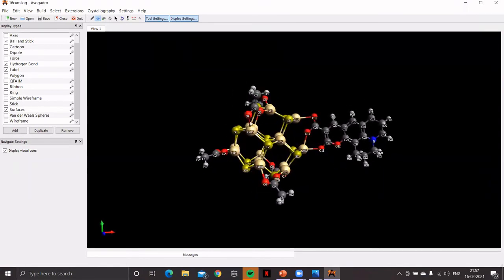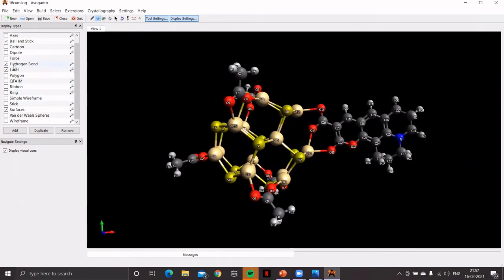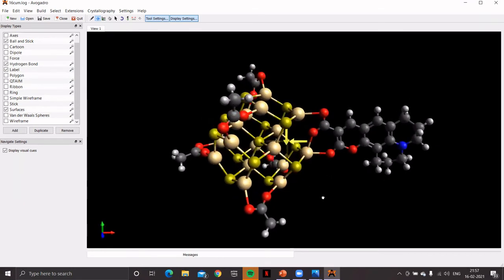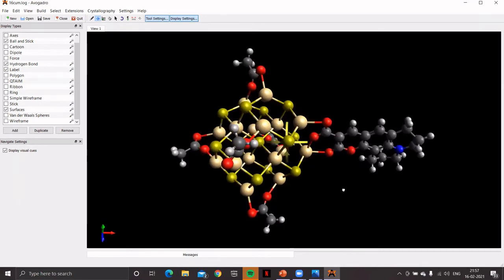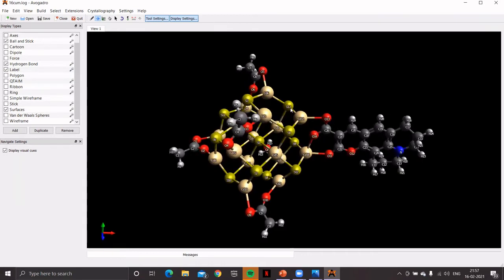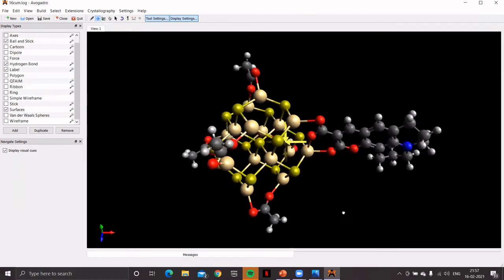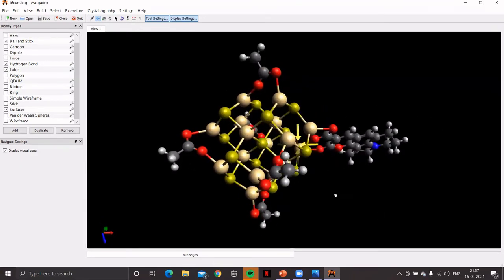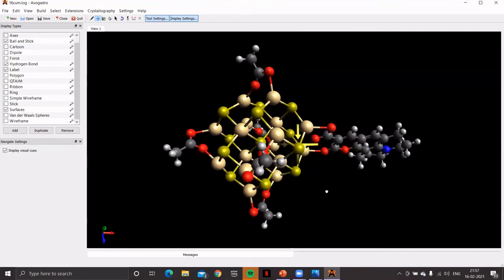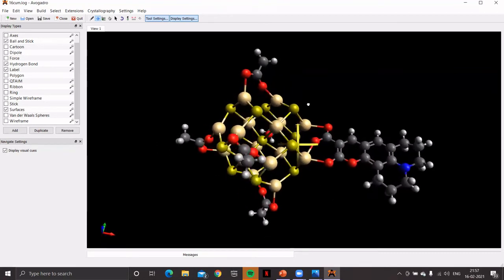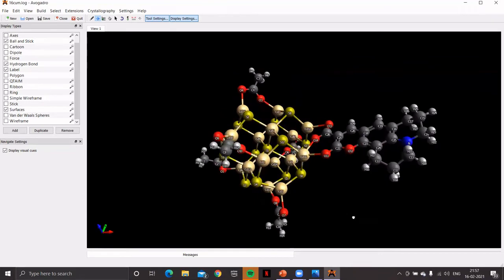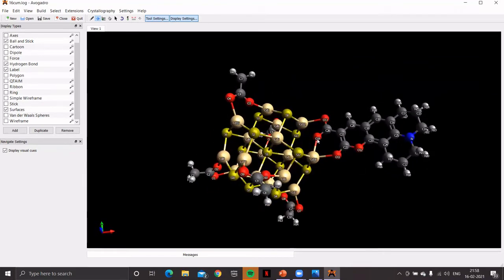So, this is the quantum dot which we have labeled them because we have checked the label option. So, the atom type and atom number is mentioned there. That's the cadmium ion and that's the sulfide ion. So, you can see that the one which is there, the bulk, has coordination number four. But the one on the surface, if you leave this oxide, then it is coordination number two. But by the help of these passivating acids, at least we tried to get the coordination number three, which is good enough.